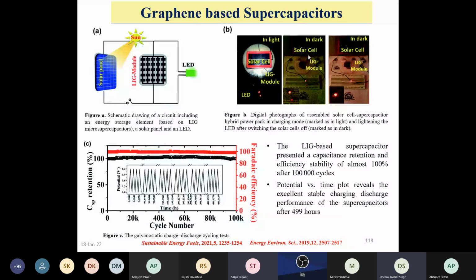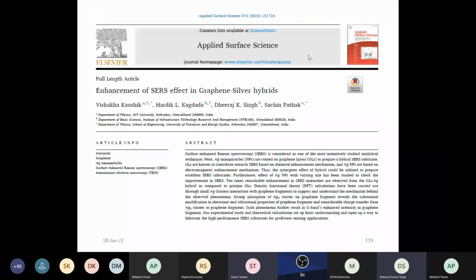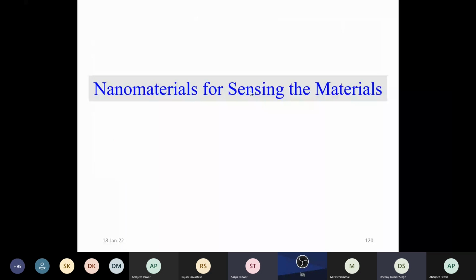And very recently, you can see we have published a research paper in Applied Surface Science. Here we have used surface enhanced Raman scattering using a graphene and silver nano hybrid. We have taken advantage of silver nanoparticles as well as graphene particles. By mixing the graphene and silver nano hybrid, we found a very important application in sensing. So now we can see the important application of metal nanoparticles in sensing.